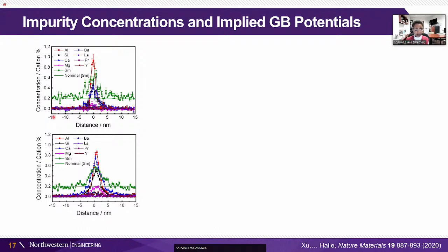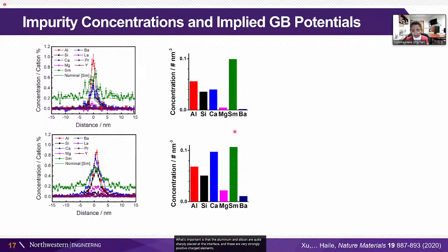So here's the concentration that we see. These are just two different examples. And the most prominent impurity is aluminum. And the next one is, our dopant is enhanced at the interface. This is kind of a known phenomenon here, that the dopants tend to go into the interface, into the grain boundary region. The next impurities are calcium and silicon and some other rare earths, which really don't impact the properties overall. What's important is that the aluminum and silicon are quite sharply placed at the interface, and these are very strongly positive charged elements. At the interface, again, this is the enhancement of the samarium dopant, and these are the impurities, the dominant impurities in the system.